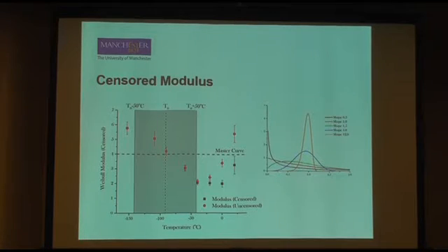And this makes sense that we're taking measured values for a ductile test and taking that as a lower bound estimate of what the fracture toughness would be if that were to proceed to cleavage. So by doing that, we're taking the ductile failures and in effect increasing the level of J in those tests. And as a result, we see an increase in modulus.